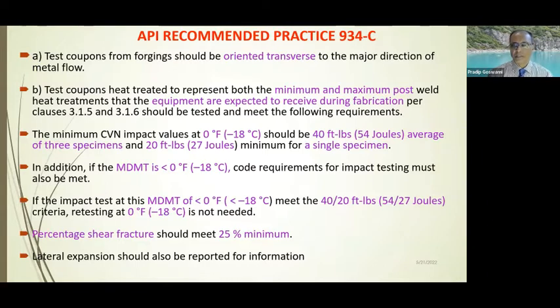So typically the requirement is that when you do the test coupon of the forgings, you take out the specimen in the transverse orientation, so that at least you know for sure that the minimum properties are being met, and they're being met well. And the minimum Charpy impact test temperature at minus 18 degrees centigrade should be 54 joules average of 3 specimens, or 20 foot-pounds, or 27 joules for a single specimen.